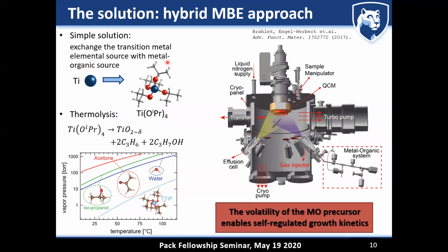Now, it turns out that if you coordinate titanium with ligands forming a metal organic molecule, the volatility of this molecule is going to be very, very high. And so you can see here that the vapor pressure of this TTIP molecule, TTIP stands for titanium tetraisopropoxide, is really high. And so the idea is that you would supply, let's say, calcium from a thermal effusion cell. You would inject this titanium-containing metal organic precursor through a gas injector. And the volatility of this titanium tetraisopropoxide is going to open that self-regulated growth window.